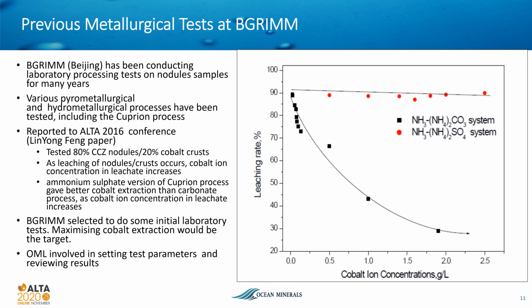In carrying out a literature review of metallurgical tests on nodules, we identified a number of potential process routes that had been evaluated since the 1970s. These included pyrometallurgical and hydrometallurgical approaches. As indicated earlier, Kennecott, under J. Agarwal, had developed an ambient pressure and low temperature ammonium carbonate leaching process called Cuprion. A low temperature and pressure process would have capital and operating cost benefits compared to most alternative routes.